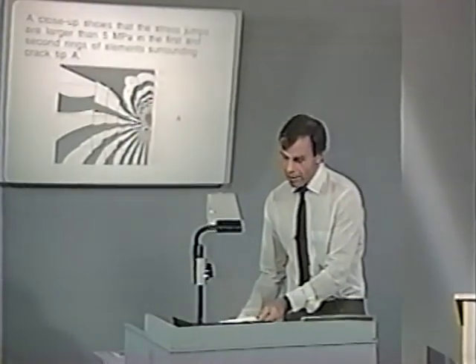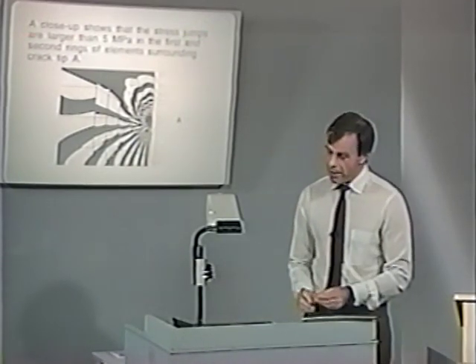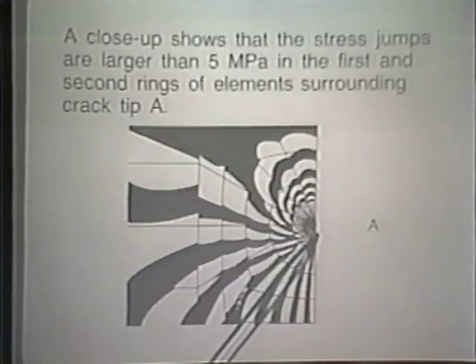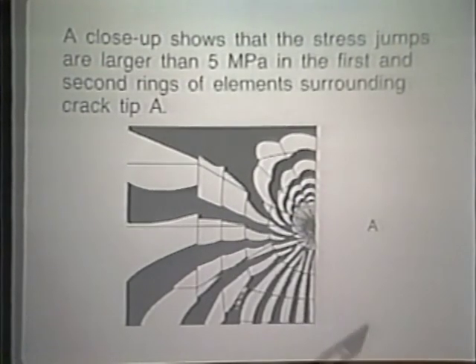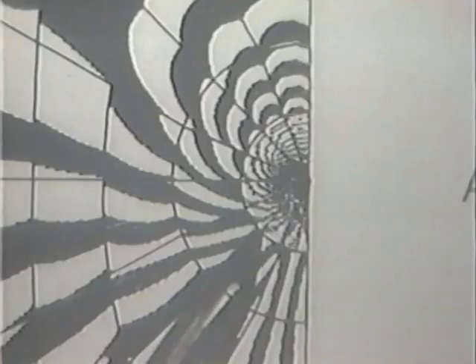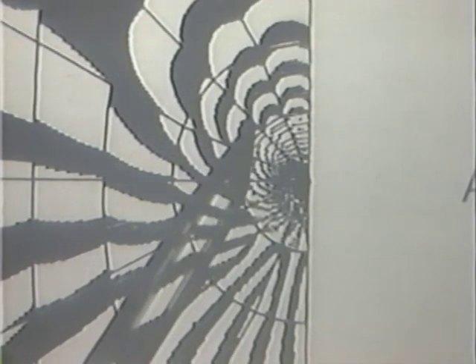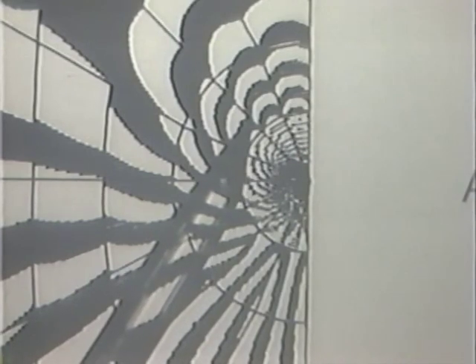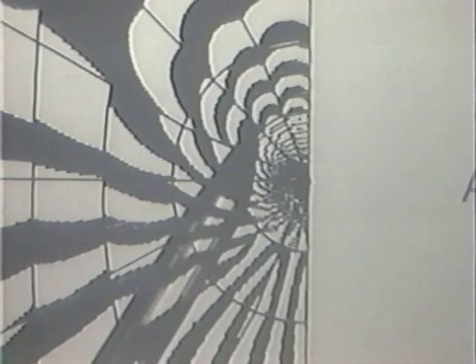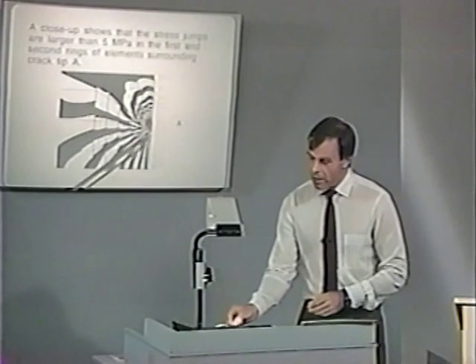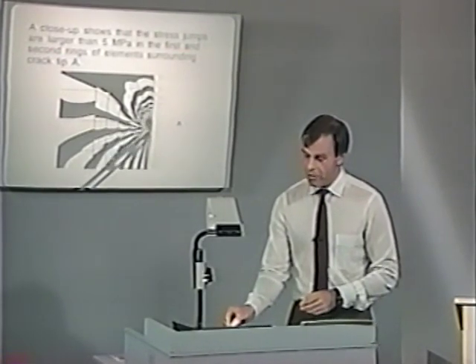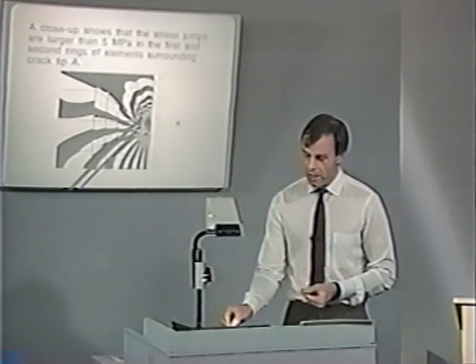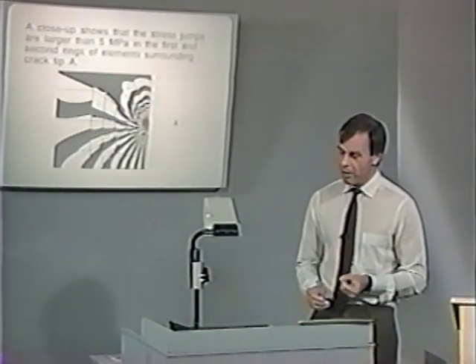If we go very close to the crack tip A, then we find that the stress jumps are, of course, large right here. You can see here breaks in the stress band. Right here, for example, a typical example, if we look very closely here, there's a black band coming into a white band. So there's clearly a break in the stress band. So here then, in this area, the stresses are not continuous and would also not be very accurately predicted.